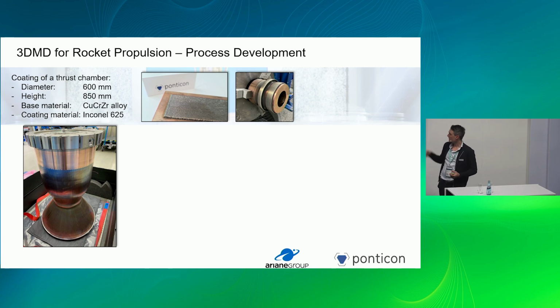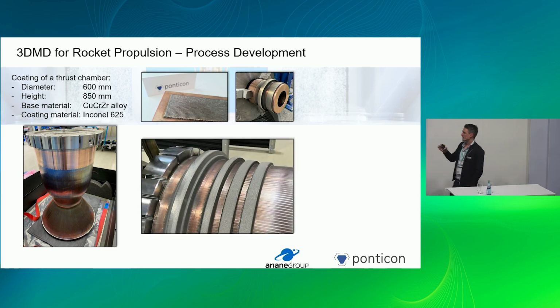So now things get cylindrical. We received a small scale sample still without the cooling channels in there. Then again applying the coatings, those thick rings on the outside for material testing purposes. So we had some tensile specimens milled from that. You will see the results in a second. And then up next, I think this is a nice close-up because you can nicely see the cooling channels underneath. We applied different process parameters, different thicknesses to also check for the residual stresses.